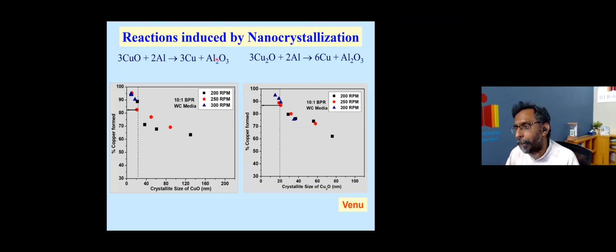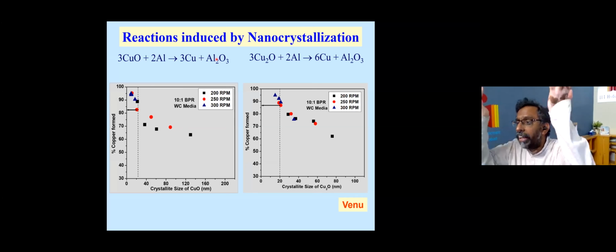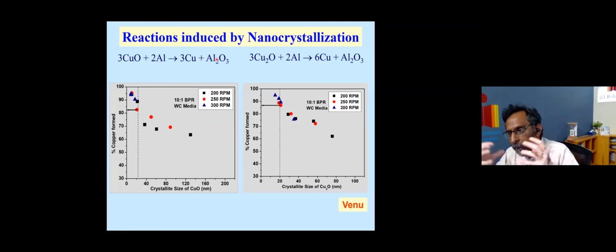You can also have reactions happening inside the ball mill, almost at room temperature. You must have seen people trying to reduce an oxide with a metal, and whenever you try to do this, you have to heat the mixture of these two to be able to reduce. Whereas here, in this technique called ball milling, you don't need to heat anything. Everything happens at room temperature just because the particles have become nano, so the reactivity enhances. And we have demonstrated that any oxide can be reduced by another metal very easily with this kind of technique. Many interesting things can be done, and all that happens below a certain particle size.